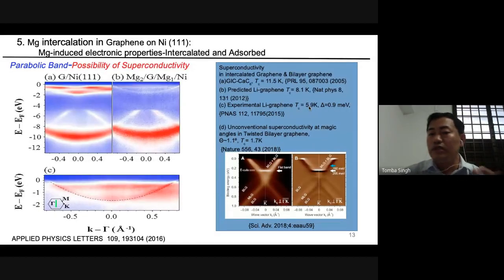This is not coming from graphene-graphene interaction; it is coming from the introduction of another layer. But recently, in 2018, a group from MIT reported that if we twist two graphene layers together, like a bilayer system, at a small rotation angle, superconducting electronic properties are observed in transport measurements. If we study the band structure, a flat band is visible at the K point. Generally, at the K point we see the Dirac cone, crossing bands. But there we observe the flat band. And the transition temperature they found is very, very small, 1.7 K.